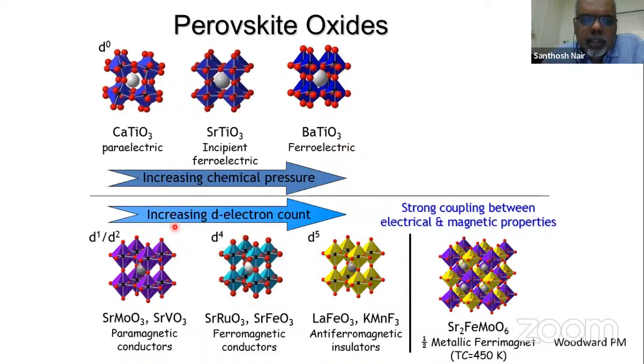The other way to do it is this: the titanium here has no d electron, no electron in this d orbital. So it's a d0 system. Now you start filling the d orbital, then you start seeing magnetic properties. For example, if you have d1, d2, in these particular systems, strontium molybdate or strontium vanadate, you get paramagnetic conductors. And if you fill in more electrons, you will get into ferromagnetic conductors. Furthermore, you get into antiferromagnetic insulators. So you can change the chemical pressure or the d electron count to achieve a large range of properties. That's pretty much what we generally do.